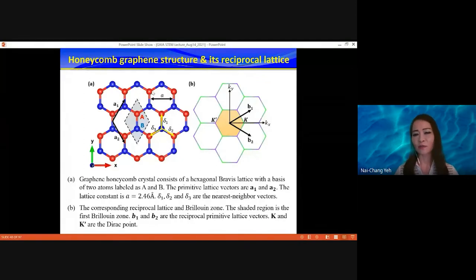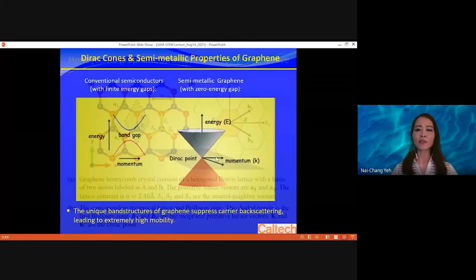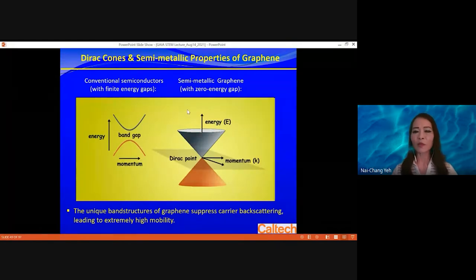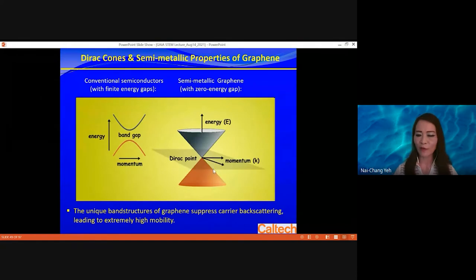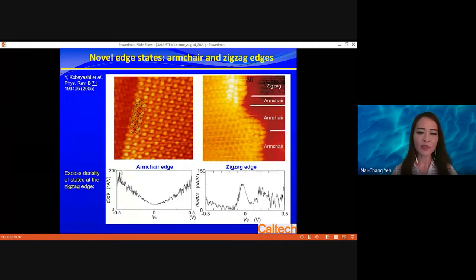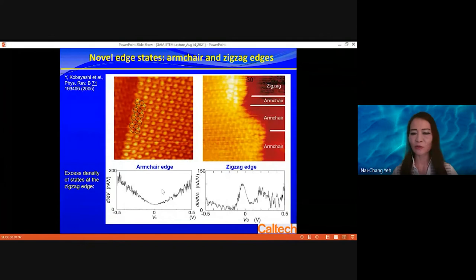You can describe the periodic structures and convert that to momentum space, giving a very interesting energy-momentum dispersion relation. For a typical semiconductor, you have a conduction band, a valence band, and an energy gap — but graphene actually has zero energy gap, and the bands look linear, meaning electrons behave almost like photons without mass. Using STM on this graphene surface, you can observe that the armchair edge shows a V-shaped tunneling spectrum, while zigzag edges look totally different — the same material has different properties along two directions.